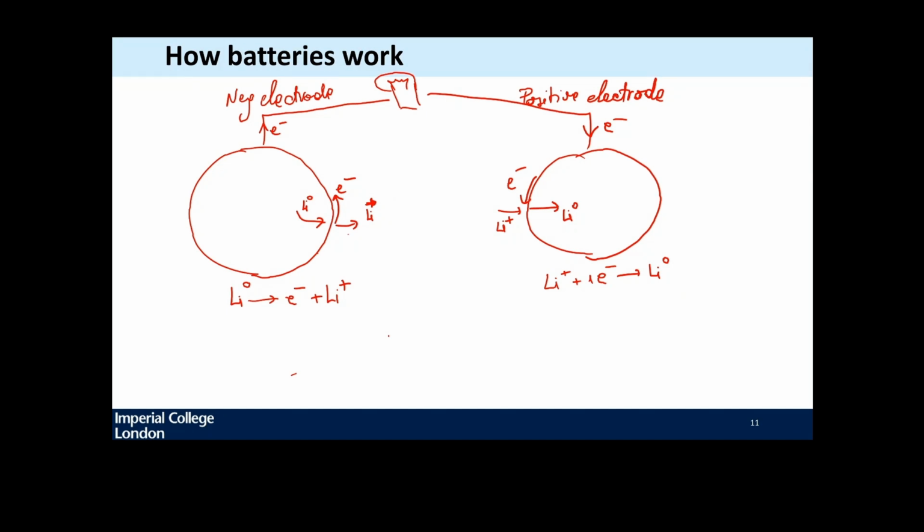And so you can already see a few mechanisms that have to happen at the same time for this battery to discharge one electron, right? I need to have lithium 0 inside the negative electrode, and it needs to be at this interface, because it's at this interface only that the electrochemical reaction happens, which provides the electrons. I need to have lithium plus available at this other interface, and this means over a long discharge that I need for lithium to diffuse